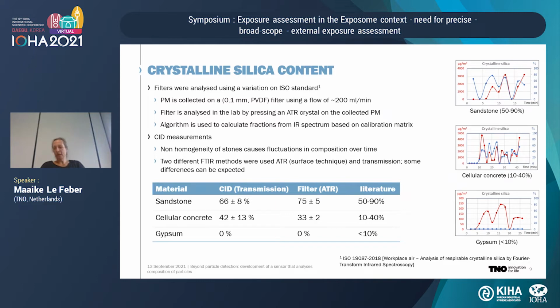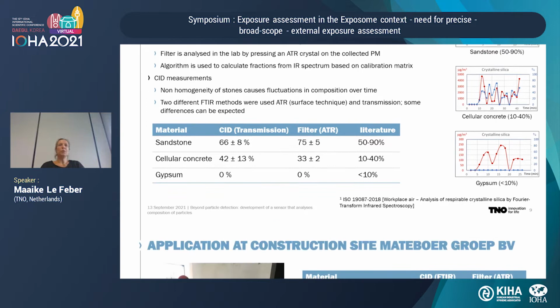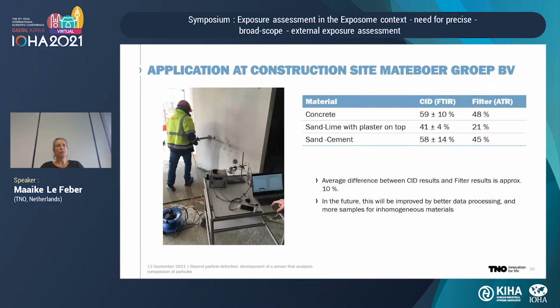So after the experiment at our own facilities, we took the devices to a construction site to see how the device performed in real life. We measured different activities and on different materials. And also here you can see that the measurements of the CID and the measurements from the filter sampling are pretty much in line, even though there is an average difference of about 10%. We expect that we can reduce this difference by better data processing and further calibration of the spectra.